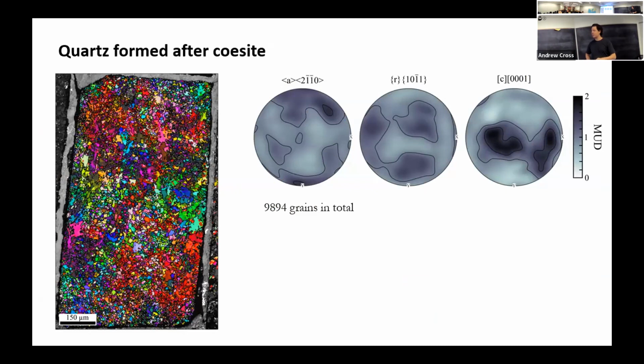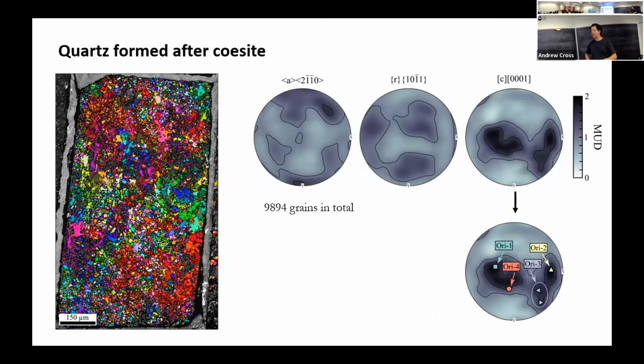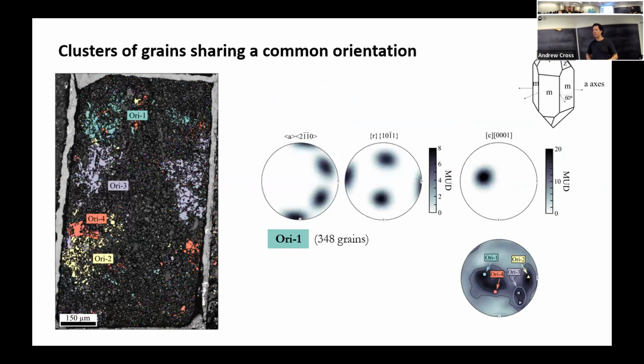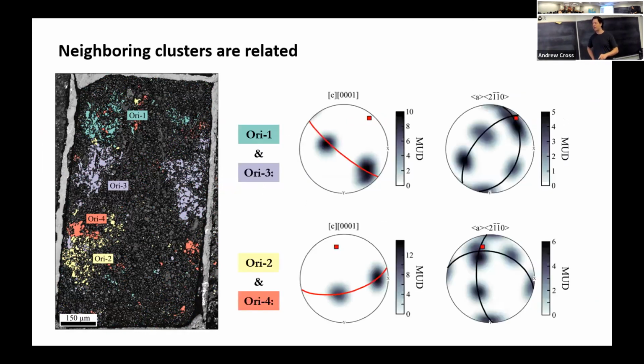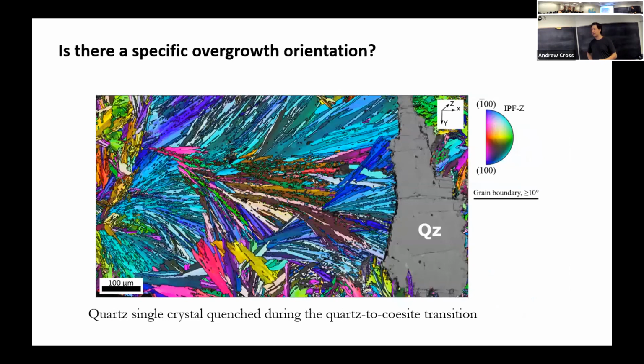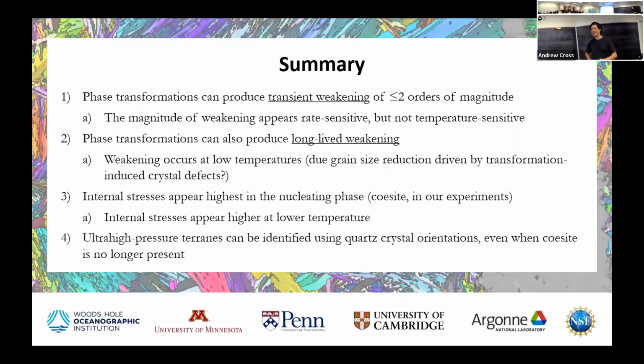And we've got a few distinct peaks in our C-axis pole figure. Our orientations tend to cluster into 4 broad groups, so we can separate out those 4 groups here. Each one of those groups, even though it's made up of hundreds of grains, has an apparently single orientation. If we look at the pole of rotation between these clusters, for orientation groups 1 and 3 that are next to each other, and groups 2 and 4 that are next to each other, they're rotated again by about 90 degrees around a common A-axis. So the same relationship holds up. And I'll leave it there.